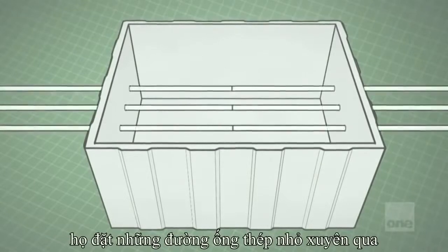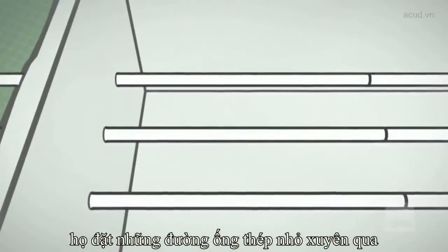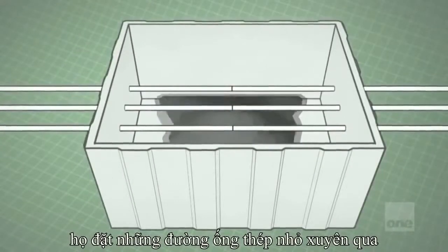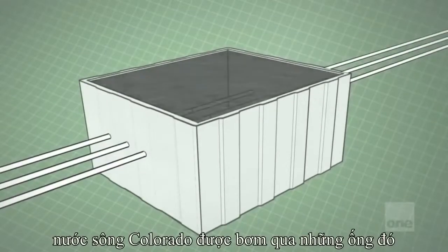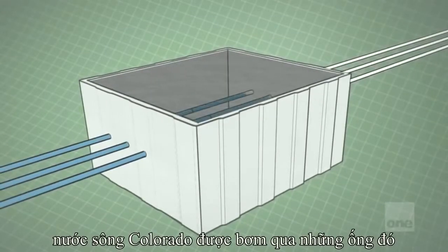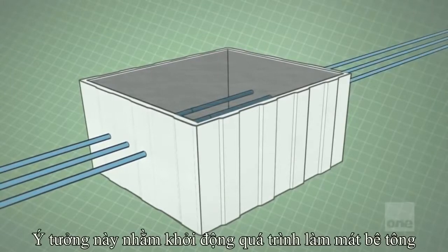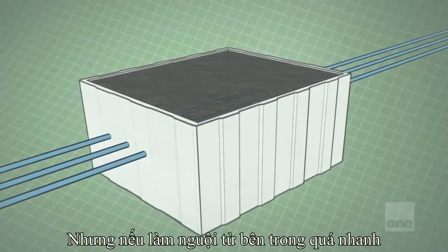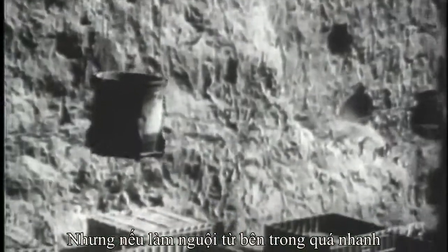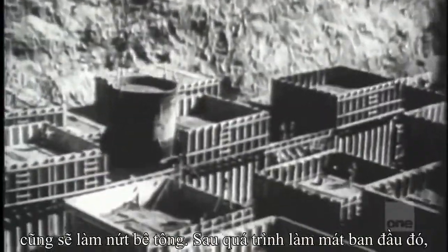Each block is outfitted with coils of thin-walled steel pipe. When the concrete is first poured, water from the Colorado River circulates through these pipes. The idea is to initiate a cooling process, but one done in stages. Cooling the concrete too quickly will cause it to crack.